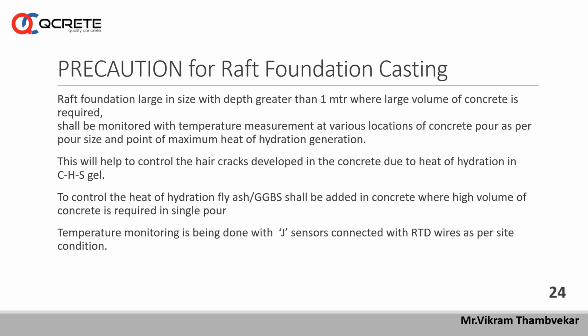So temperature monitoring is a very important factor for a raft foundation, because in other cases, see, large size columns and of course beams and slabs are not much bigger, but when a girder is there, or a retaining wall or lift wall, where the wall itself is designed as an RCC member, at such a member, concreting should be done in stages, not more than 1 meter height, to avoid all this problem of heat of hydration, as well as to compact the concrete to a very good degree.